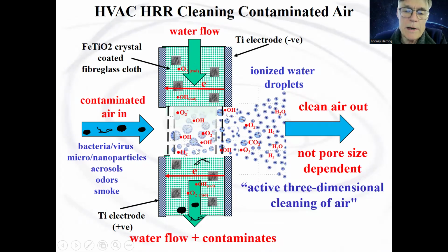And then when the water passes through the pores of the fiberglass cloth, air passes through, and we find that it's able to remove things like bacteria, nanoparticles, aerosols, odors, and smoke. And we get those, and we can collect these contaminants in a reservoir below. And what's nice about this air filter, it's not pore size dependent like HEPA filters. It's an active three-dimensional air filter.